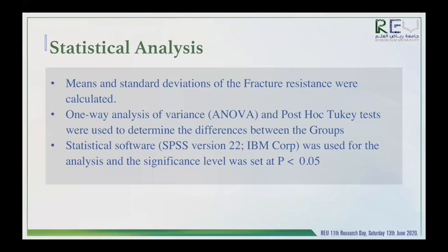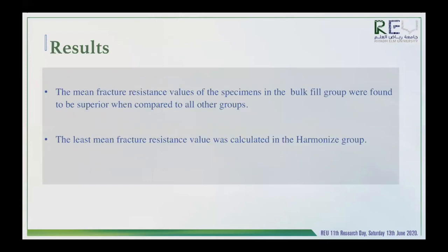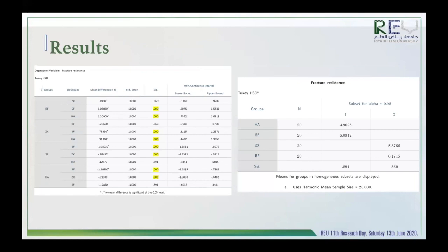Statistical analysis: mean and standard deviation of the fracture resistance were calculated. One-way analysis of variance ANOVA and post-hoc Tukey test were used to determine the differences between the groups. Statistical software SPSS version 22 was used for analysis, and the significance level was set at p-value less than or equal to 0.05. As we can see here in the table, the mean fracture resistance values of the specimens in the bulk fill group were found to be superior when compared to all other groups. The least mean fracture resistance value was calculated in the Harmonize group.